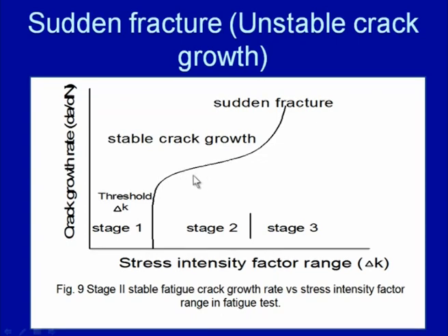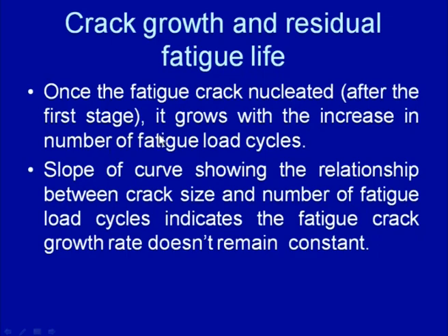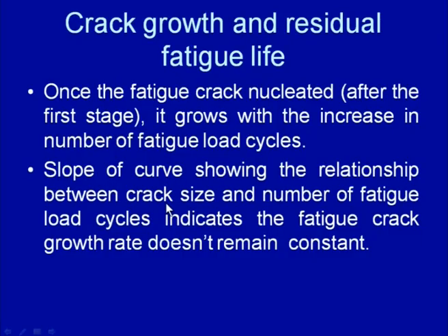Mainly the fatigue life of the component is dictated by the rate at which the crack growth occurs in the second stage, and the higher the crack growth rate, the lower the life of the component under fatigue conditions. Then how can we identify the residual fatigue life when the crack is growing? We know that once the fatigue crack nucleates after the first stage, it grows with the increase in the number of load cycles, and the slope of the curve showing the relationship between the crack size and the number of fatigue load cycles indicates the fatigue crack growth rate, and it does not remain constant.